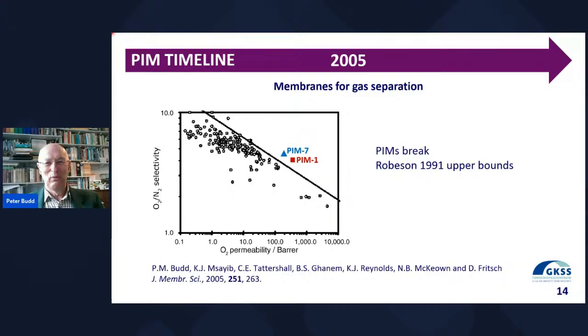And we looked initially at two PIMs, PIM-1, which I've mentioned, and also another PIM, which we call PIM-7. And the interesting thing is that we found that we did have polymers which were much more permeable than most polymers, perhaps not quite as permeable as poly(trimethylsilylpropyne) (PTMSP), but more permeable than most polymers, whilst being relatively selective.